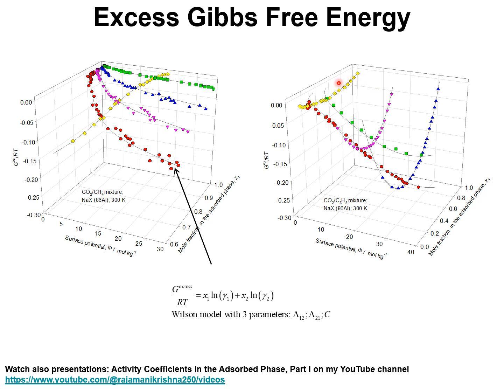Also in this case, the set of 5 CBMC simulations are analyzed simultaneously to determine the 3 Wilson parameters and the Wilson fits of the activity coefficients, and are used to determine the excess Gibbs free energy, and these are shown by the continuous solid lines here.